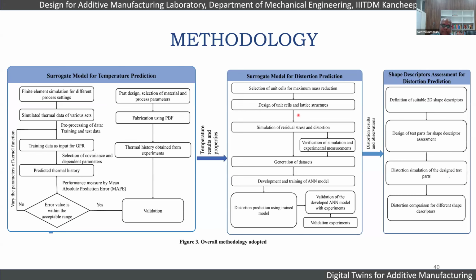And the second part, we did this to prove that it works in the mesoscale. We took some complex structures which are very unique for 3D printing. One of the things that we have selected is a strut-based lattice. You can even choose surface-based lattices, but we used strut-based lattices to prove that a distortion prediction technique can predict faster with respect to those kinds of very intricate geometry. So that's the methodology that we have adopted. We designed the unit cell for the lattice structure, simulated the residual stress and distortion. We generated the data sets, and then we trained an artificial neural network model, which is our surrogate model for the macro scale. And then we very uniquely defined something known as shape descriptors, which can even fast track the simulation by evaluating 2D shape descriptors from the 3D part.